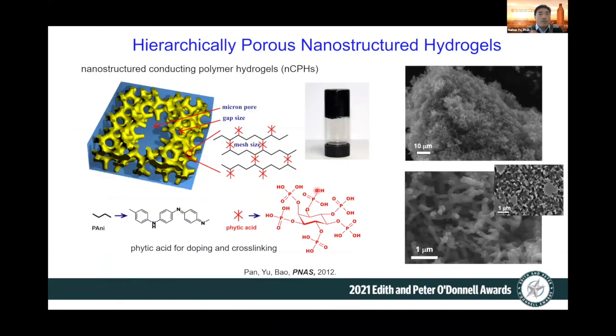The first example is a 3D hierarchically porous conducting polymer hydrogel. Here we use polyaniline as an example. Polyaniline is very special: it has alternating single and double bonds, which give it good electronic conductivity. We studied various factors, including phytic acid as both dopant and cross-linker. Phytic acid is a naturally abundant material that exists in plants. You can see it is highly populated with phosphoric acid groups, so it can serve as the cross-linker to cross-link the polymer monomers.